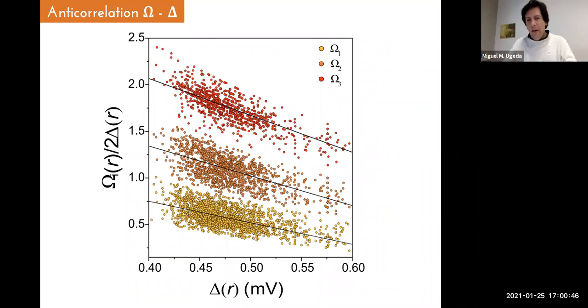We have taken all of the curves that I showed you in the first histogram. We have studied the position of the mode, for the fundamental mode and for the first two harmonics, normalized to 2 delta and plotted against the value of the gap at that particular point for each curve. And as you can see, in all of the cases, they follow an anticorrelation. So basically, we believe this is a strong indication that the peaks that we see are spin excitations as well, in analogy to the most known unconventional superconductors.